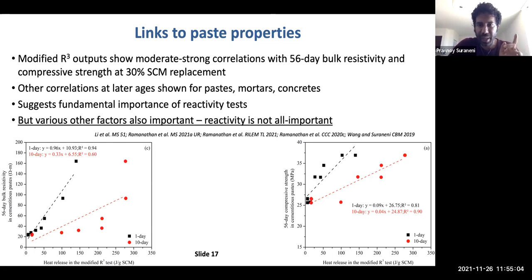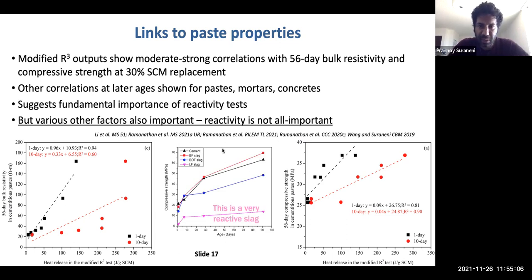A specific example is in this particular case, we had 3 different slags that we tested, and the most reactive slag, this was a slag that was extremely reactive, actually does not generate strength at all, compared to these 2 slags, which were not particularly reactive, but they generated quite a bit of strength.